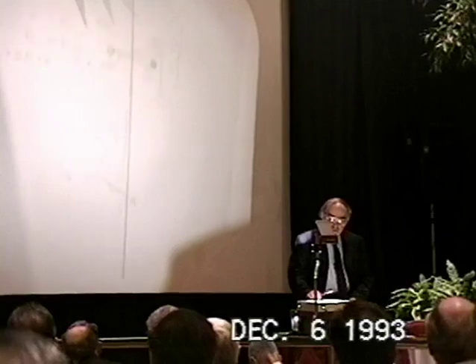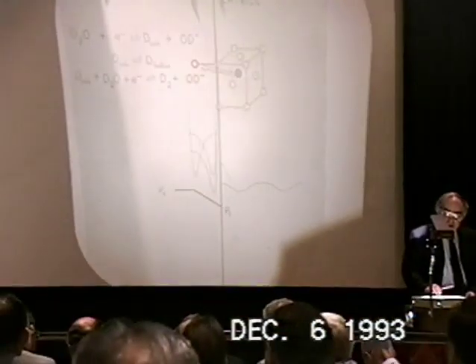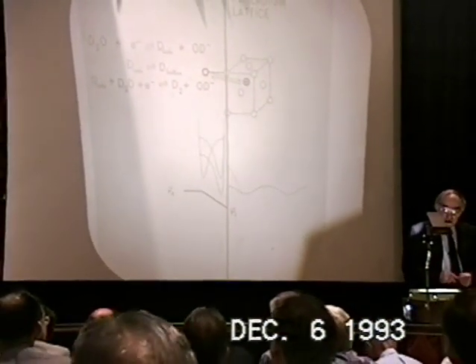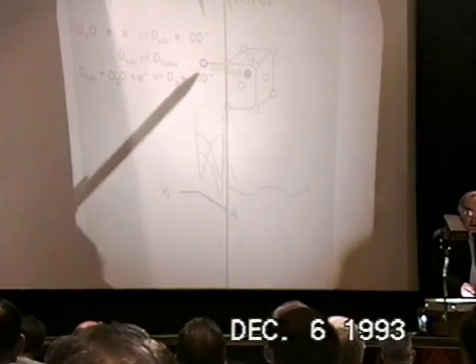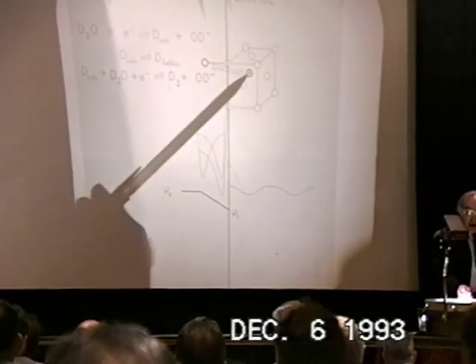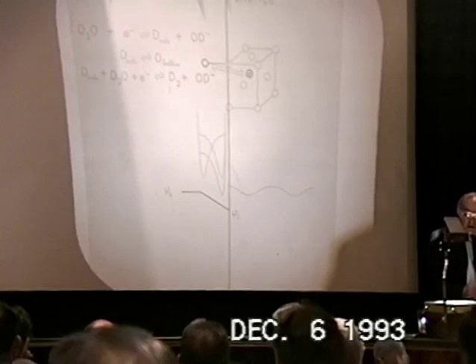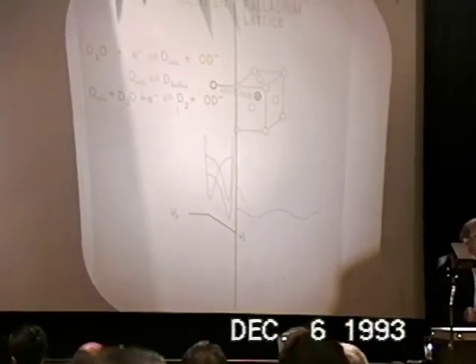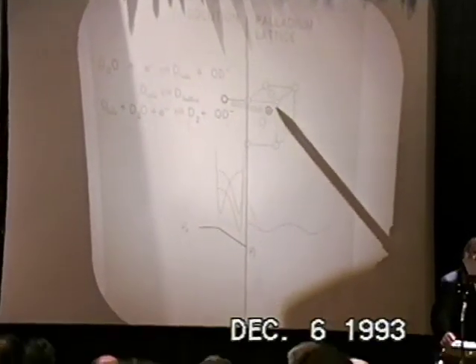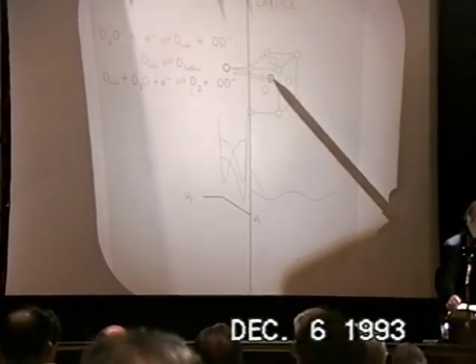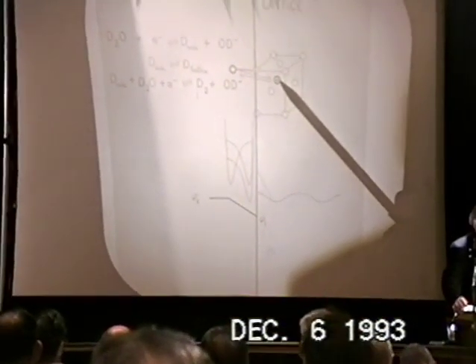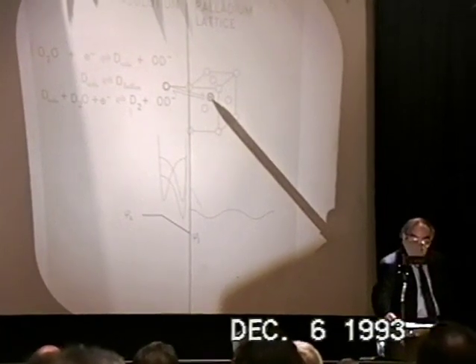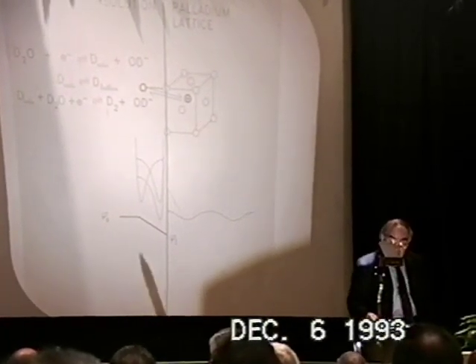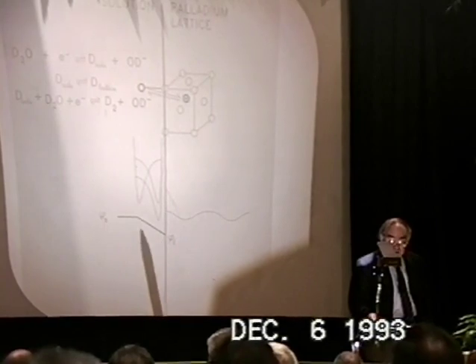Well, as you all know, it is widely believed that we are interested in inserting deuterons into the palladium lattice and increasing the electrochemical potential of the species, the activity of the species in the lattice, by applying a difference in galvanic potential.